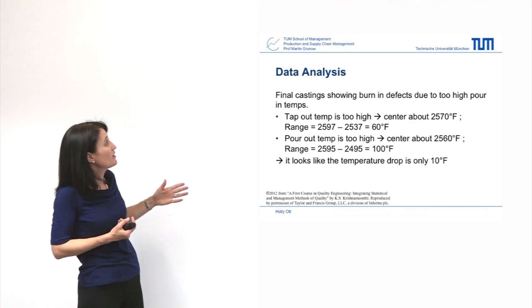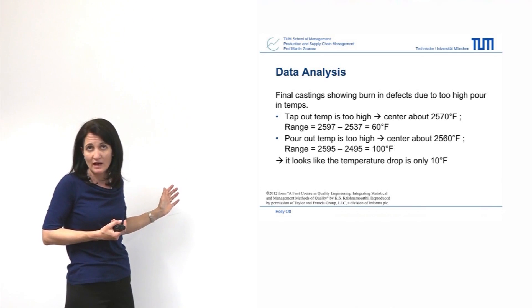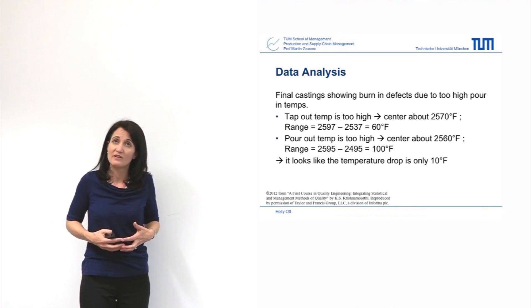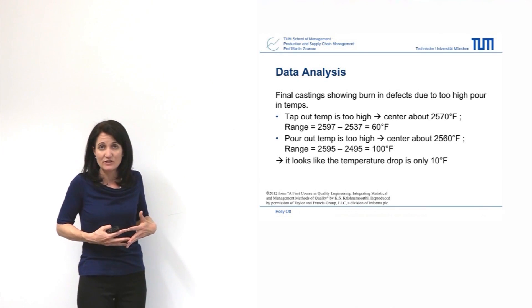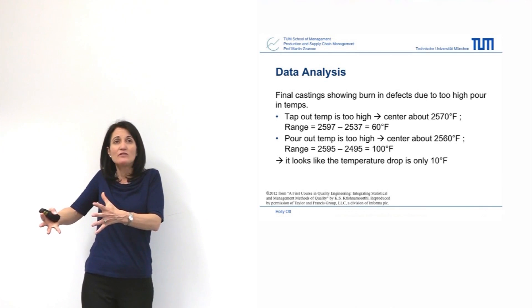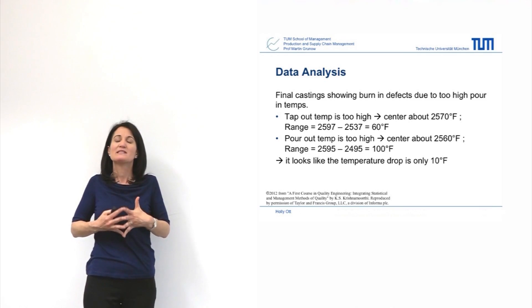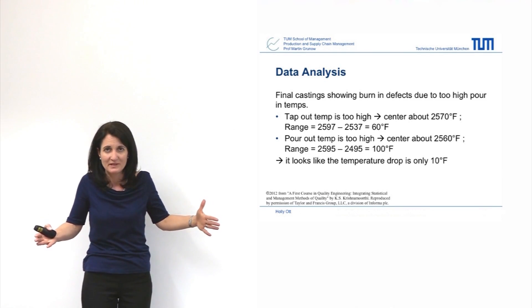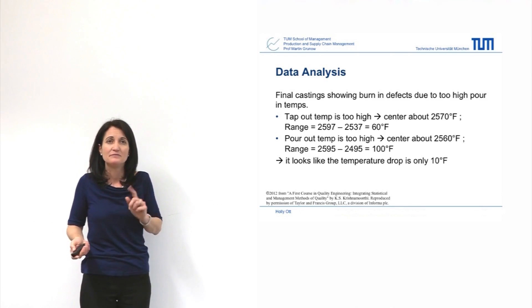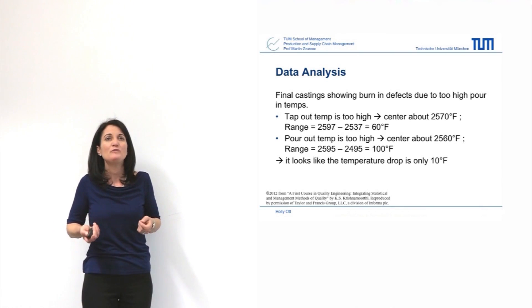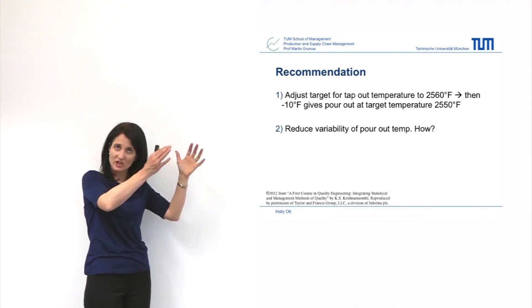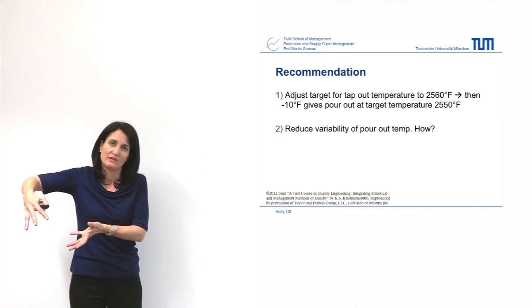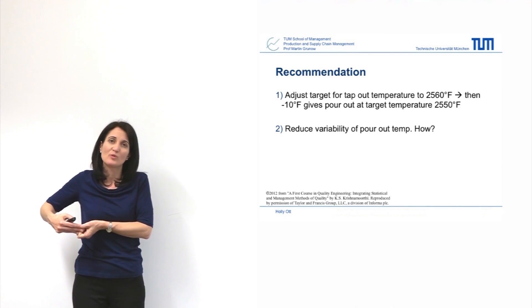To summarize the data: we're getting burning defects due to too high a pouring temperature. The tap-out temperature is centered at about 2,570 degrees Fahrenheit with a range of about 60 degrees Fahrenheit. Once the molten metal travels to the pouring phase, it's centered at 2,560 degrees, meaning the initial estimation of a 20-degree drop is too high — it should be more like 10 degrees. So we're going to adjust the tap-out temperature 10 degrees lower, then when it drops 10 degrees, we will pour it at the target temperature of 2,550. That brings your process to target.